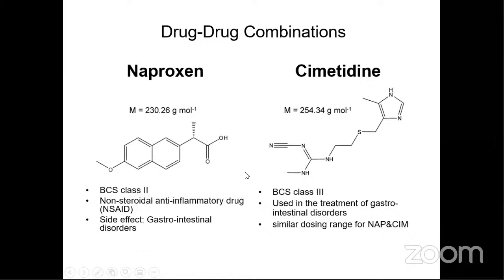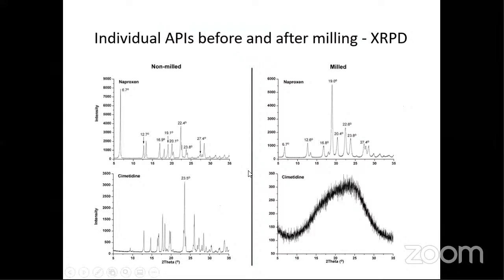This is why we do this: we use these two compounds mixed together and try to prepare amorphous compounds. Here are the individual APIs before and after milling - this is non-milled, before-milled crystalline naproxen and crystalline cimetidine. We can see the peaks, and after milling, pure naproxen cannot become amorphous after milling.